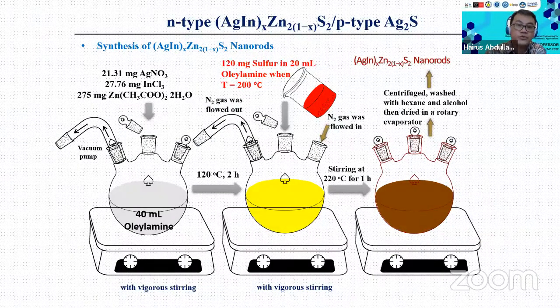So first of all, I would like to show you a very simple synthesis method. This is done in oleylamine solvent. So we just take all the necessary precursors for this AgInZnS. We take the Ag nitrate, indium chloride, zinc acetate dihydrate, and put into this oleylamine solution, and apply vacuum to pull out all the atmospheric air. Then after 120 degrees for 2 hours, we inject the sulfur source. The sulfur source is actually dissolved in oleylamine first.